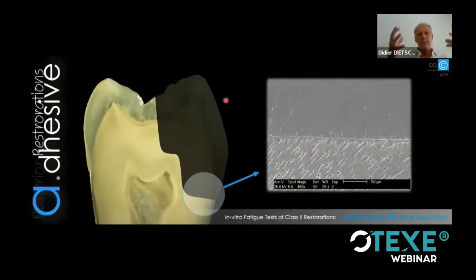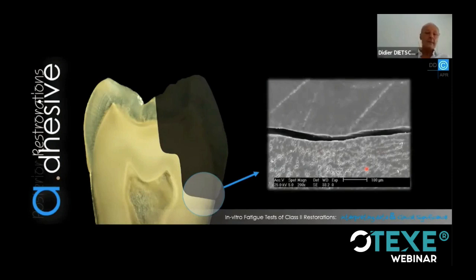And in fact, before and after the mechanical loading, we analyze the margins, either enamel or dentin, and what we wish to see is what you have here, a perfect adaptation between the composite and the dentin. But sometimes it doesn't work. And we have a debonding, we have a failure of the adhesive interface. And that is actually when the problem starts. Because if you look at the size of this gap, it's maybe 10 or 20 microns. It's a highway for bacteria.